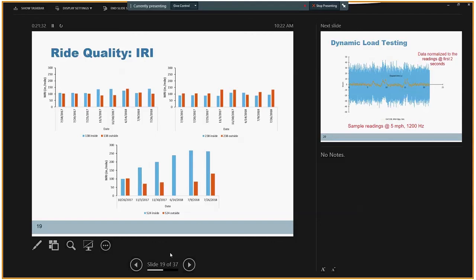There seems to be some increase, but we will just continue monitoring the IRI values and see the trend in increase in IRI for these concrete mixtures. The graph we have at the bottom of this slide shows the IRI values for the reference concrete. Again, the blue lines are inside lane exposed to traffic, and we see there is a clear linear trend of increase in IRI values over time. That means reduced surface quality and reduced ride quality for reference concrete over time, which will definitely have something to do with the lower thickness of this concrete, 6-inch versus 8-inch compared to the 2 other sections.